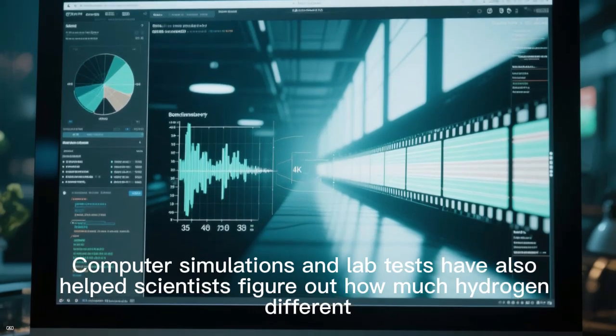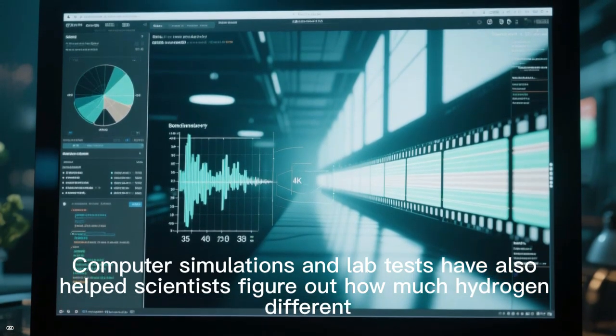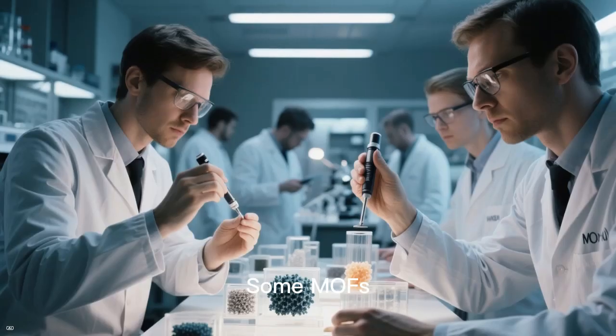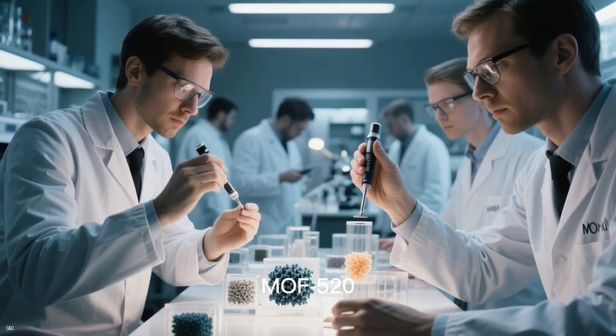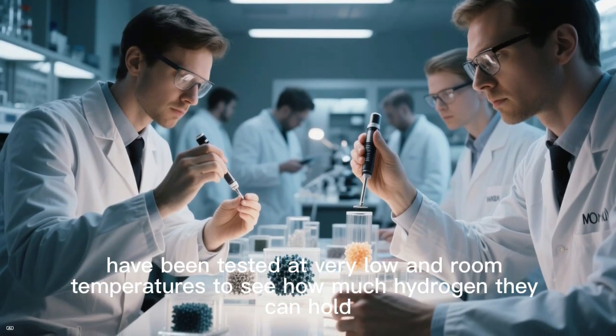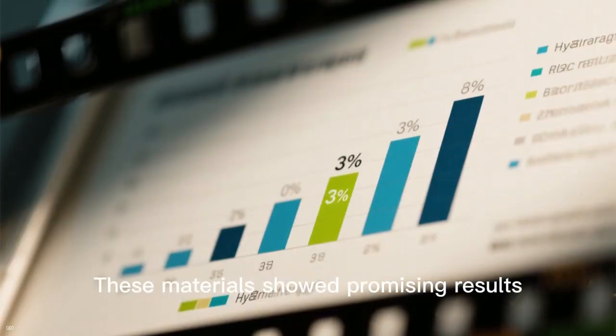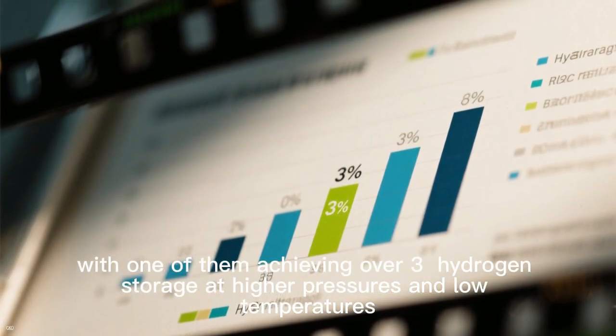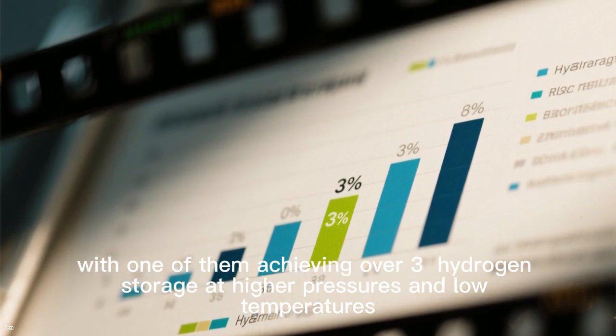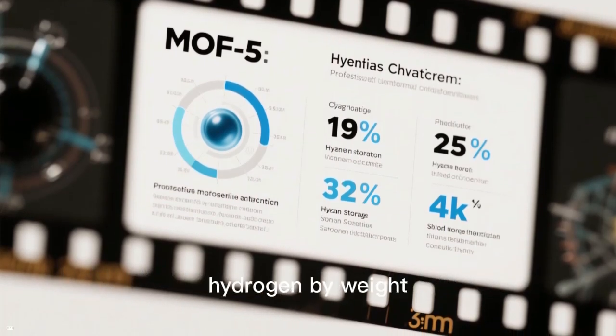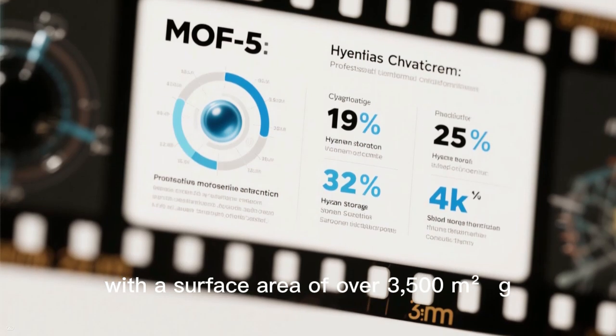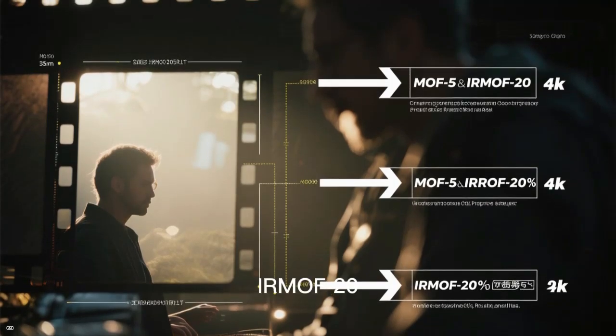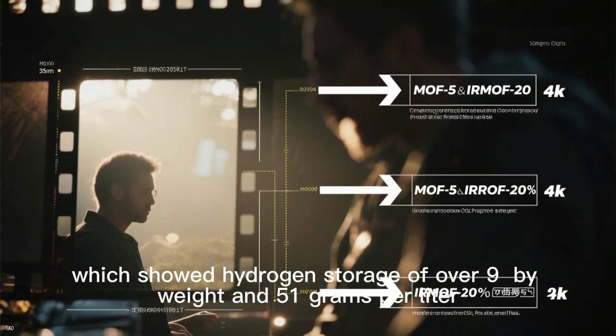Computer simulations and lab tests have also helped scientists figure out how much hydrogen different MOFs can store under different conditions. Some MOFs, like MOF519 and MOF520, have been tested at very low and room temperatures to see how much hydrogen they can hold. These materials showed promising results, with one of them achieving over 3% hydrogen storage at higher pressures and low temperatures. A well-known MOF called MOF-5 was shown to store up to 6.8% hydrogen by weight, with a surface area of over 3,500 square meters per gram. Even more impressive results were seen with another MOF, IRMOF20, which showed hydrogen storage of over 9% by weight and 51 grams per liter, meaning it was both lightweight and space efficient.